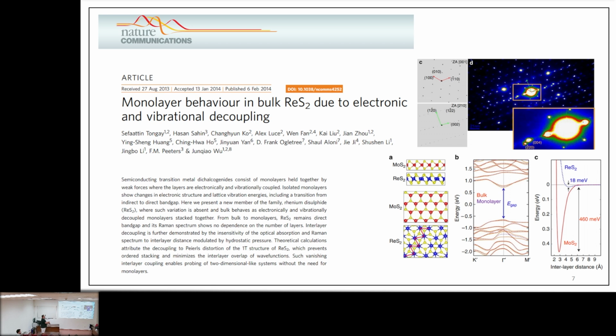This is the top view, as you know. And after my calculations, I noticed that rhenium disulfide is not a semiconductor as other TMDC materials. So it's a semiconductor, but with a direct band gap. And structurally, it has a very different type of structure with a distortion. So in this paper, I contributed to that part. And you see, for experimentalists, sometimes it's not that easy to determine what is the atomic structure there, because it's very thin, it's invisible. But from theory, you can have some hints about the structure.